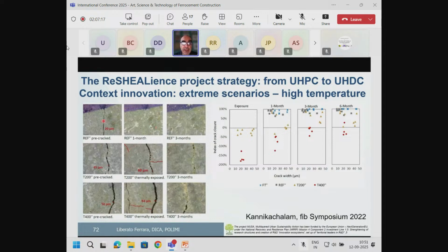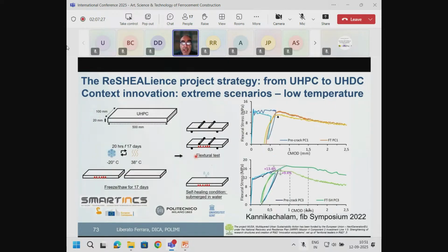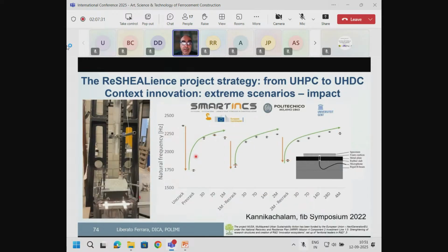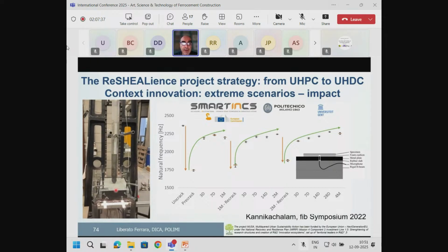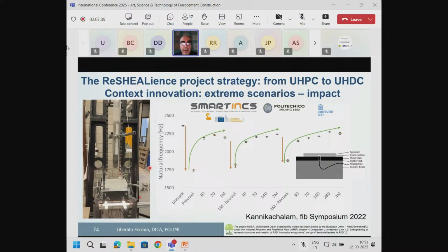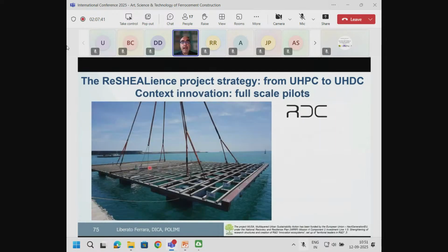As you can see from these images, this is the reference material. This is the material exposed to 200 degrees, and this is material exposed up to 400 degrees. And you can see that the cracks were closed. We also proved this in freeze and thaw materials. We proved this material under impact. You can see this very thin slab, just a few centimeters thick. There was a recovery of the natural frequency, and other pilot structures that were built by the consortium of the